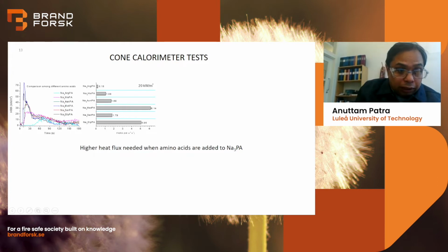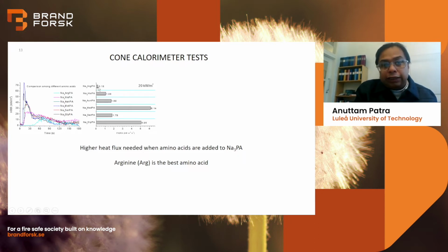If you put a normal untreated cloth, it will be very high, more than 200 kilowatt per meter square in HRR value. But when you have amino acid, it decreases a lot. Especially one amino acid called arginine shows a very interesting result. The HRR decreases very much, and not only that, the peak comes very late. It makes the FIGRA index very low. Remember, the lower the FIGRA index is, the better the flame retardant.